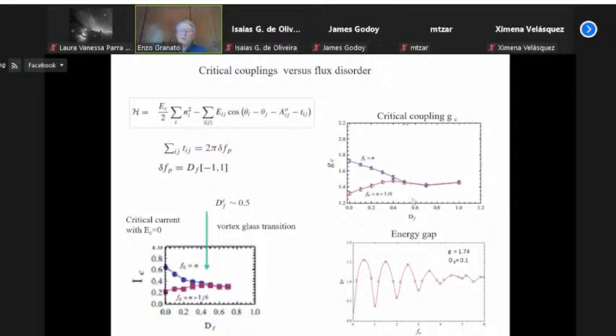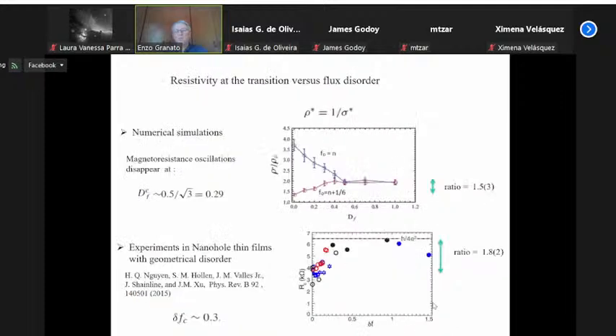The point at which they merge here is related to a transition to a glass phase, in which the disorder is so large that the vortices introduced by the magnetic field sit in a disordered region. And this can be shown by calculating the critical current and temperature. On the right here, we show the energy gap just above the transition as a function of frustration, and you see it oscillates as a function of frustration, as you see experimentally, and disappears at a particular value of the frustration, which is similar to what you find experimentally.